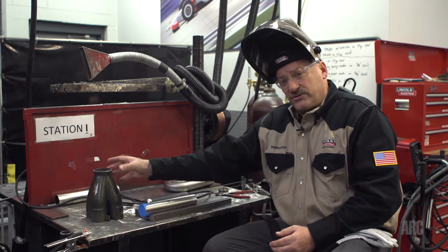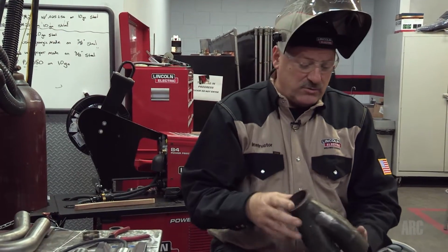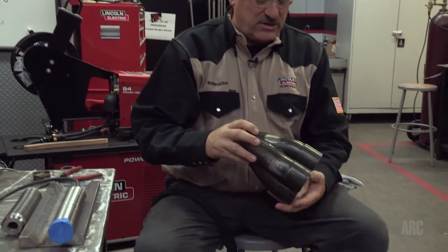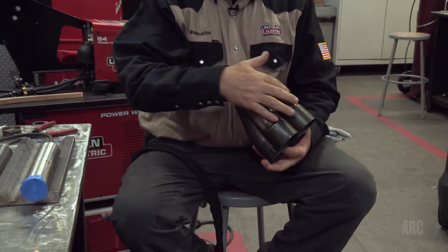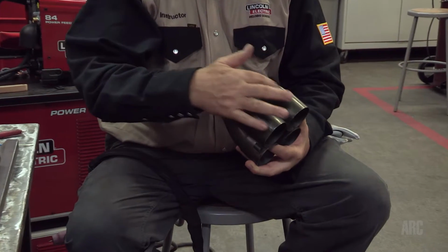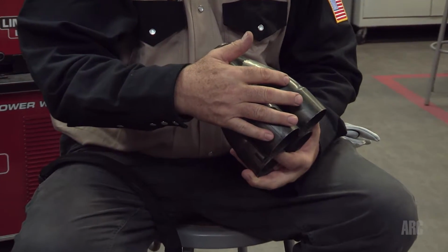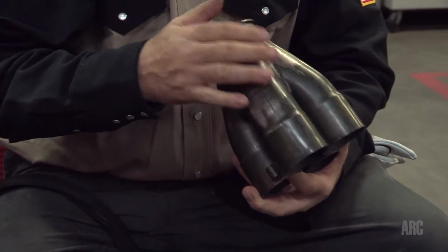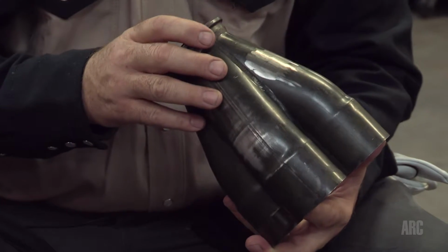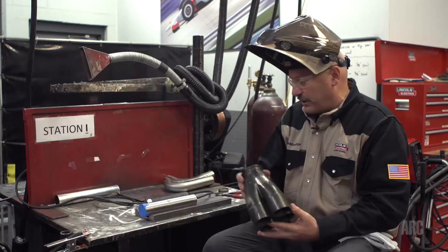I have a couple parts here. This is a used collector for probably an Indy racing team, and you can see that this part has been operated at high temperatures. It has a dark oxide coating on the surface. The oxide's been sanded off. This is probably operated at 1800 degrees to get that oxide coating.